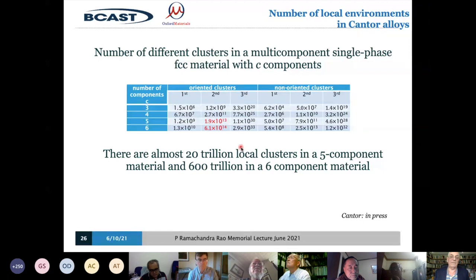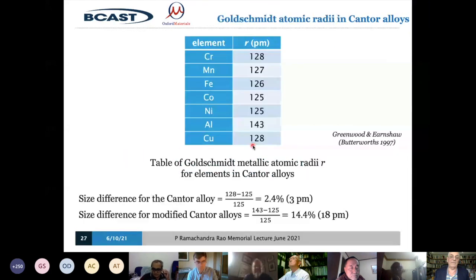So there are literally trillions and trillions of these local environments, and they're all associated with a small strain. Well, the strain isn't actually that small, but the difference in size is. So here are the five initial Cantor alloy elements. They have sizes which are quite similar, ranging from 125 to 128 picometers. The difference is 3 picometers. Even I can do that maths. 3 picometers is the difference, but that's about 2.5%. 2.5% in strain terms is quite a lot. So the lattice is locally strained as you move through it.